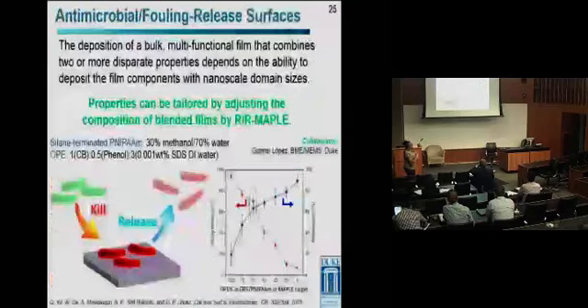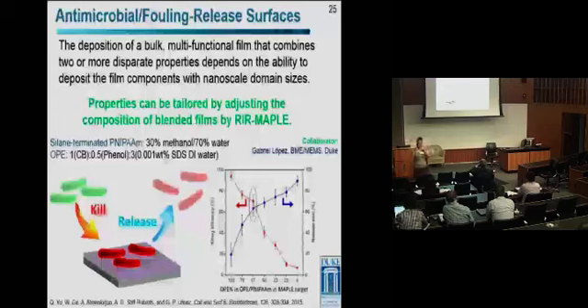The thing that's really interesting, though, is that we combined both together. We had that antimicrobial OPE, and we had the stimuli-responsive polymer that could release the bacteria, and now you have a multifunctional surface that can attach bacteria, kill them, and release the bacteria to regenerate the surface so it can be reused. And we've demonstrated that type of cycling. In this case, what we showed was that just by changing the percentage of the antimicrobial component in the target, we could control the functionality of the film. As the amount of the antimicrobial component increases, the killing efficiency increases. At the same time, the release function to regenerate the surface decreases, and we can find an optimum composition.